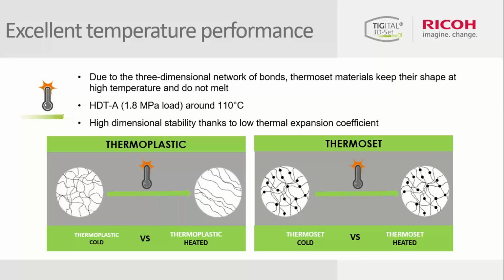So also just to give you some figures for comparison in terms of thermal performance of this material, their heat deflection temperature A could be up to 110 degrees, which is higher compared to the heat deflection temperature in the same condition for a typical nylon 12, even a flame retardant nylon 12 material, which generally has an HDT of around 80-84 degrees. And also, this material has a very low coefficient of thermal expansion, which also contributes to the high dimensional stability.